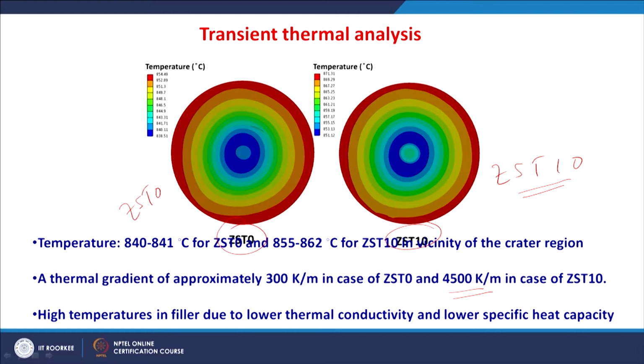High temperatures are also observed in the filler material, mainly because of its lower thermal conductivity compared to these two samples, either ZS T0 or ZS T10. Compared to these two sample materials, the thermal conductivity of the filler material is very low. So, conduction is difficult in the region of this filler, and you get high temperatures at the filler regions. This can also be due to the lower specific heat capacity of the filler compared to these two materials.